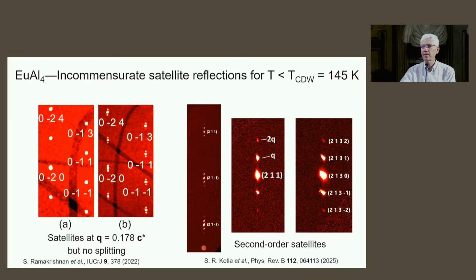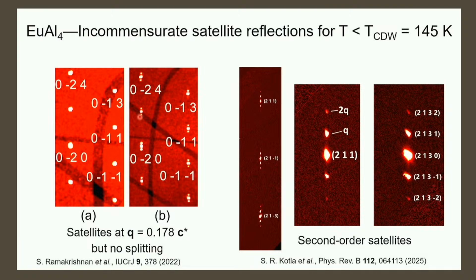And that's our diffraction. On the left, our earlier diffraction with only first order satellites, and then we made better crystals. And you can see here second order satellites. So we got a data set with second order satellites.